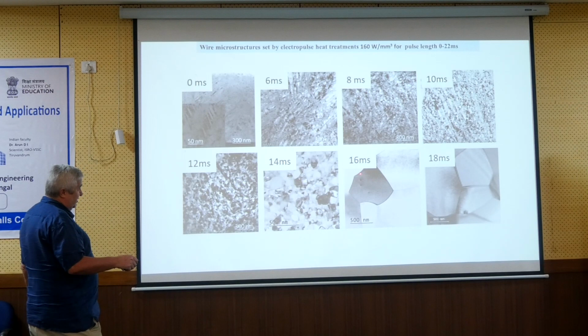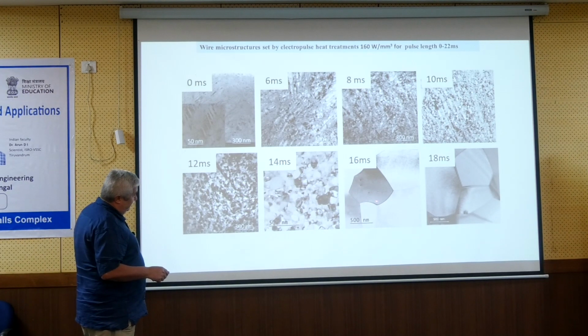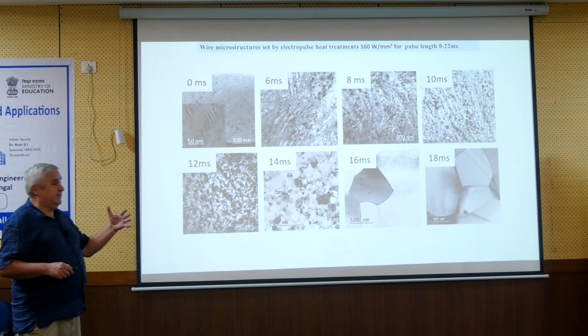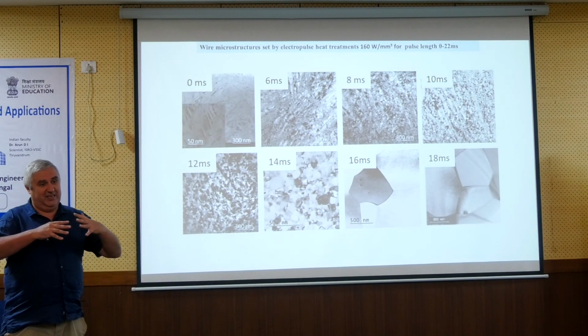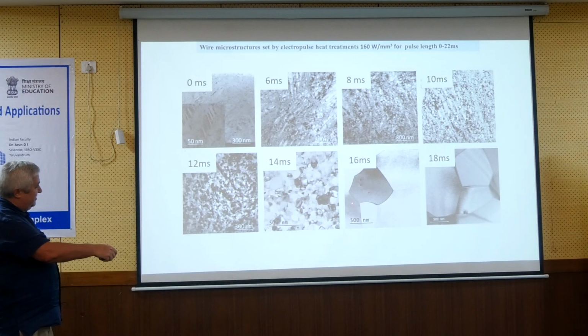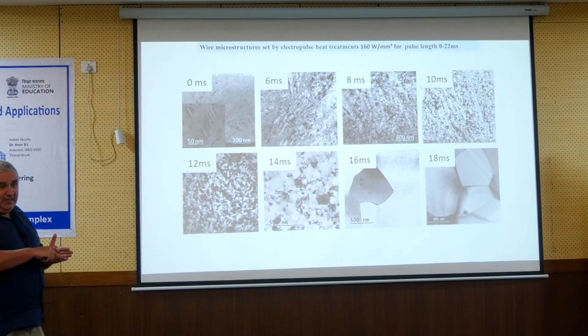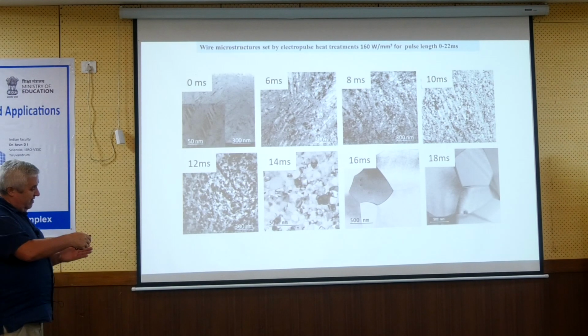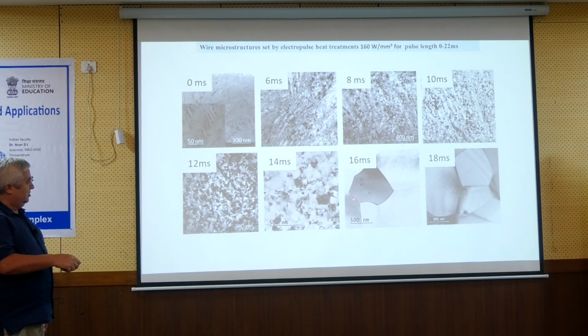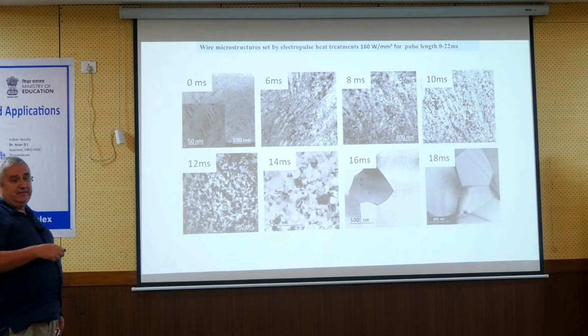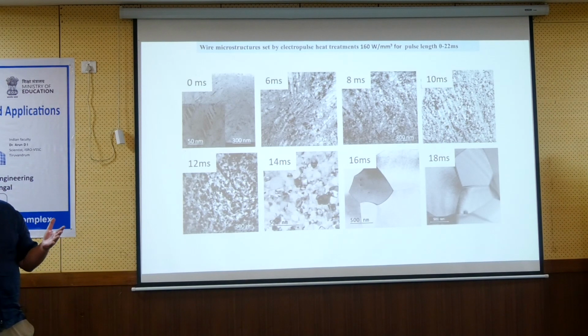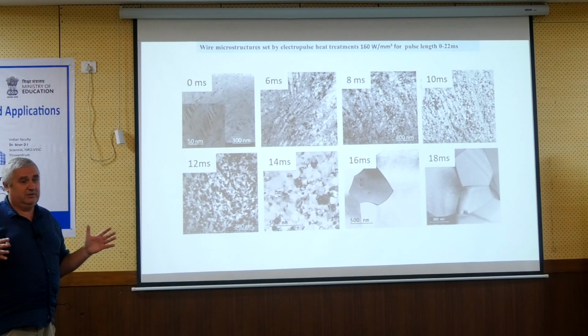Also, you see these kinds of arcs over here. The people who study grain growth understand this very well. This is how, when the grain becomes bigger, it grows with such a shape of the grain boundaries. Because we heat and then we stop at some moment, we are freezing the grain during the grain growth. You know? So here it's like 500 nanometers, here it is like 1 micron and 6 microns. And all this happens in millisecond time. With electric current you can make it very precise. It doesn't depend on time, on anything.